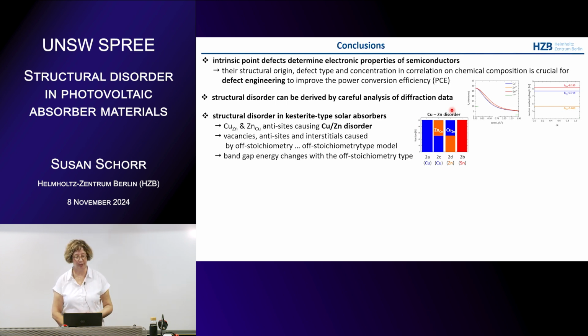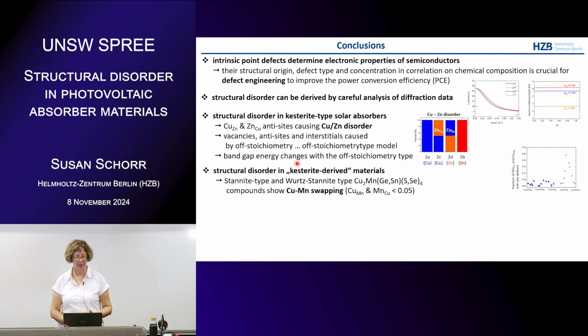I showed you the structural disorder in kesterite-type solar cells, especially the copper-zinc disorder, vacancies, antisites, and interstitials caused by off-stoichiometry. We have the off-stoichiometry type model for that now. And we also could show that the bandgap energy changes with the off-stoichiometry type. I showed you the disorder in the kesterite-derived materials like copper manganese germanium tin sulfide selenide, which have a stannite-type or wurtz-stannite-type structure, and they show the copper-manganese swapping. That means these two antisite defects, copper on manganese and manganese on copper, are less than 5%.